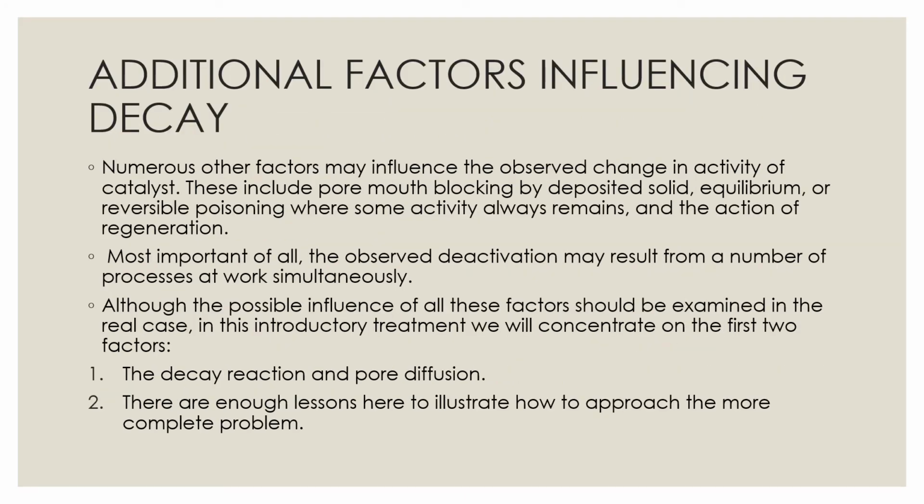Now moving on to the last factor, that is, additional factors influencing the decay. All the other factors that contribute are minor factors, and we have clubbed them together. Numerous other factors may influence the observed change in the activity of the catalyst. These include pore mouth blocking by deposited solid, equilibrium or reversible poisoning where some activity always remains, and the action of regeneration.